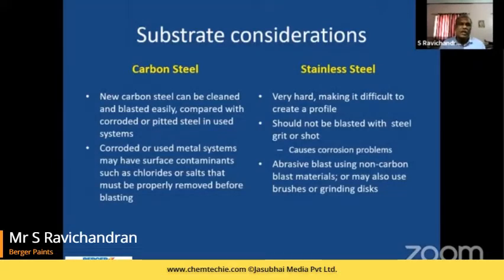And we need to ensure that there are no chlorides or salt contamination on the pitted areas during the process of cleaning. So efficient amount of surface preparation has to be given, be it carbon steel or stainless steel. When it is stainless steel, we have to be all the more careful because chloride ingress can cause pitting corrosion, and the pitting can really make a hole through the steel. So we have to be very careful, and many of the pitting is not visible to the eye. So we have to have a careful inspection before preparation.